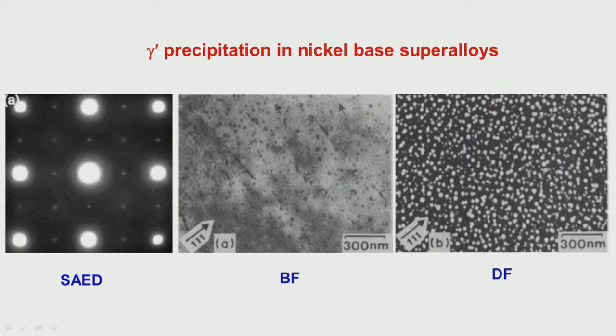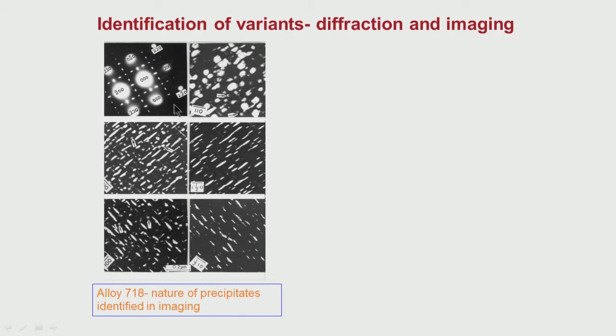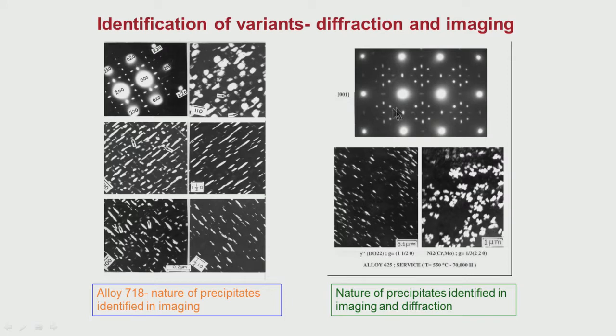In this particular case which I have considered, there is only one type of precipitate. There are cases where we can have more than one type of precipitate. Here there are three variants of the same phase, and choosing different diffraction spots and taking dark field images, I can identify how different variants are oriented in the matrix. That information we could see. This will be explained later in detail in other classes.